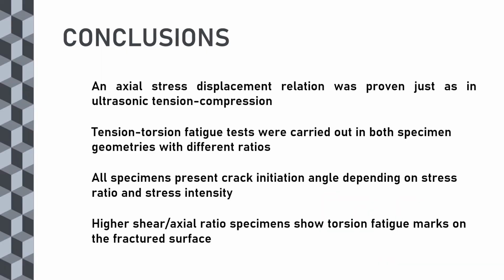Now, the conclusions taken from this work. We tested two different geometries in tension and torsion. These geometries had different stress ratios. Through the behavior analysis of the specimens, we have proven a linear stress displacement relation very similar to the one observed in ultrasonic tension compression methods. Through the analysis of the fatigue fracture, we have seen that crack initiation angle and the characteristics of the fatigue fracture surface are dependent on the stress ratio and the stress intensity applied. Now, the higher the shear/axial ratio is, torsion fatigue marks appear and the crack initiation angle is higher.